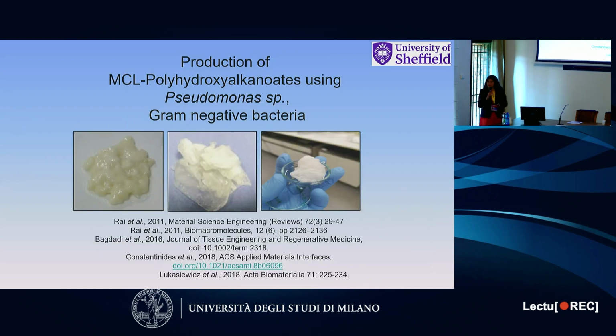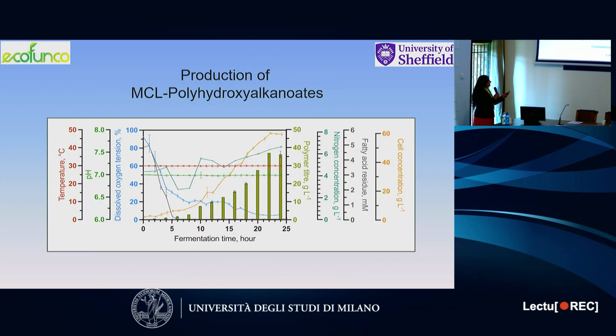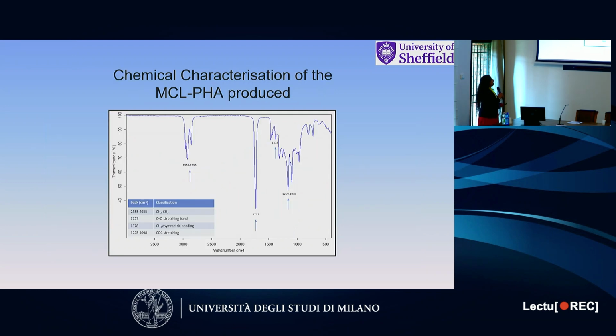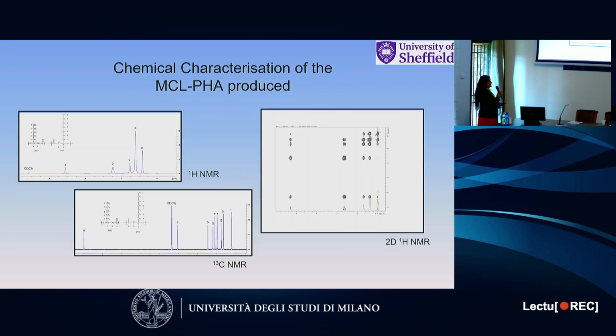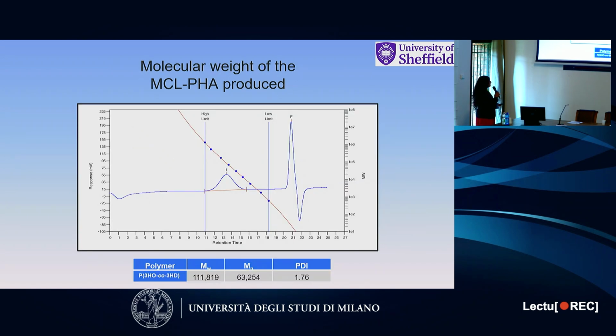I also produce the highly elastomeric ones. We have about 7 different types in our laboratory, and these are extremely elastomeric in nature. Again, a very controlled fermentation process is used for the production, and we ensure that the chemical structure is exactly what we want. So we do FTIR spectroscopy, we do NMR, and ensure that we have exactly what we think it is. With the GPC, you can see here the PDI is even lower, about 1.76, and the molecular weight is slightly lower than the previous polymer, but quite high otherwise.